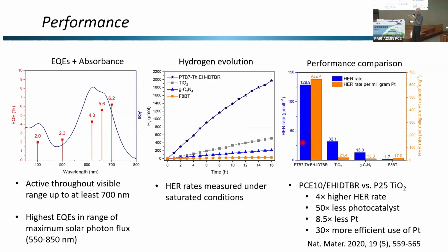And you can see that this is our EQE as a function of wavelength in the visible, not dramatically great, right? So we really need to get this up. So the target for hydrogen evolution is roughly $1 a kilogram. You're not going to achieve this with EQEs under 2%. So we still need to increase this a little bit.